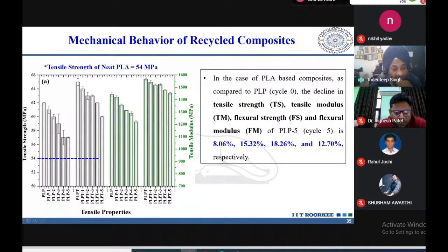Then after first recycling, as I showed you in the previous slide, that we can recycle the process waste multiple times. So after first recycling, although the properties are reducing, still these are more than the neat PLA. Even after 5 stages or 5 levels of recycling, the tensile strength that we achieved for the fiber reinforced polylactic acid composite is still more than the PLA. Which establishes the fact that these materials are recyclable. We can recycle them multiple times and achieve properties which are better than the neat polymer.